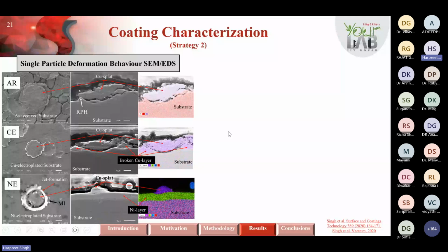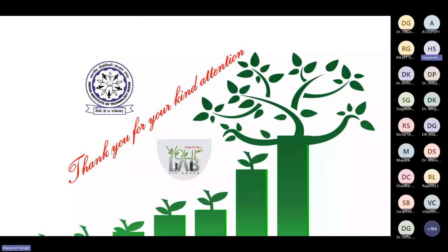by this electroplating route, we will say we need a very thin electroplated nickel layer before we deposit the copper, but not copper over copper, because the electroplated copper does not have the required strength, and it broke away. And again, we did not see the right bond here. So these are different types of studies.